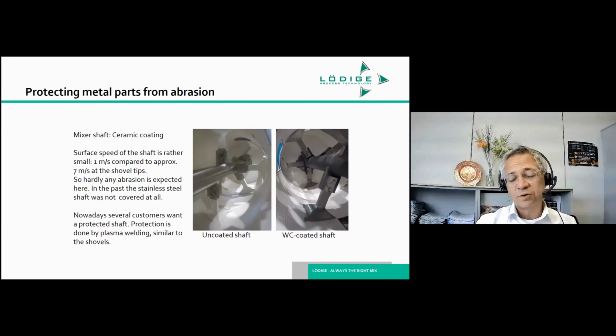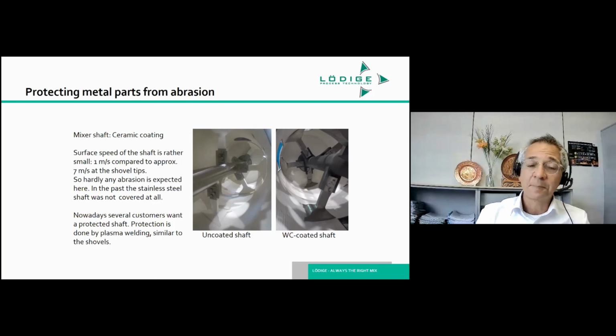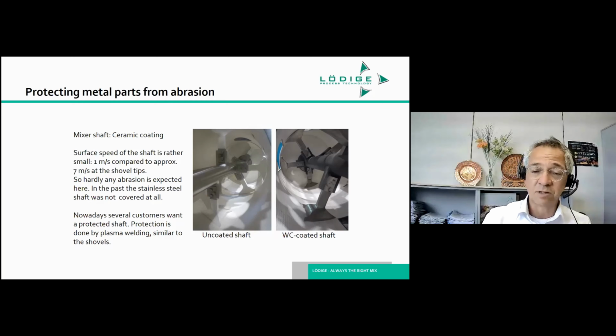Because once you start looking into areas where potential contamination can be in mixing, then you look at each individual item in turn. And again, over the course of 10 years, you can see here, the left and the right picture are machines which are around 10 years apart. And on the left side, you see that only the mixing drum and the mixing elements were coated, and the mixing shaft was untreated because, of course, the areas of most abrasion were deemed to be the mixing drum, where the material rubs against it, and the mixing tools, which plunge into the product and basically move the product and are subjected to friction and abrasion. But the mixing shaft, being in the center of the machine, was deemed to be not so dramatic for this, because it moves with relatively small tip speeds, and hence friction and abrasion were deemed limited.